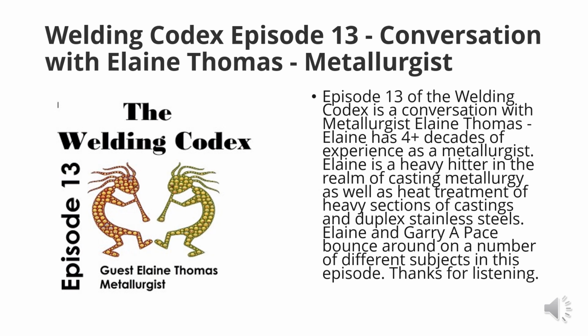You're right about that. We've been working in ASTM to get rid of the phrase repair weld, which infers that there was something wrong with the casting. The welding and grinding that you mention is really part of the casting process. So we're trying to go back to the phrase production welding. I think that's really the correct phrase to use. Right, because it's not like the part had been out in the field in use and something was wrong and you were fixing it. You're just using a different process to add material to where maybe it didn't flow when it was originally supposed to go there. Right. It's an interesting thing.